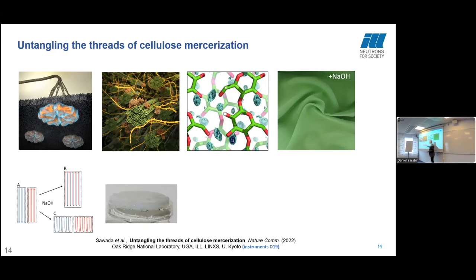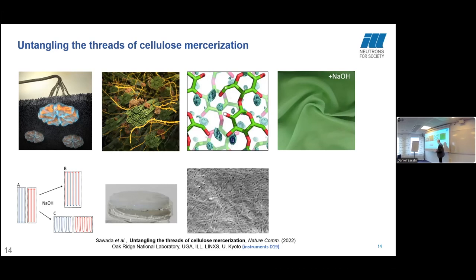So we spent years, literally years, growing cellulose from a certain type of bacterium that produces a pellicle of cellulose, and adapting that bacterium to grow in deuterated media so that the pellicle is completely deuterated. So the nanocrystals are deuterated. And then it took us years to find a way to free up those nanocrystals and then orient them into fibers for fiber diffraction. So we made pellicles of deuterated and hydrogenous cellulose. We oriented them so we had samples like this: 50% deuterated, 50% hydrogenous. Then we mercerized it, then we collected neutron data.